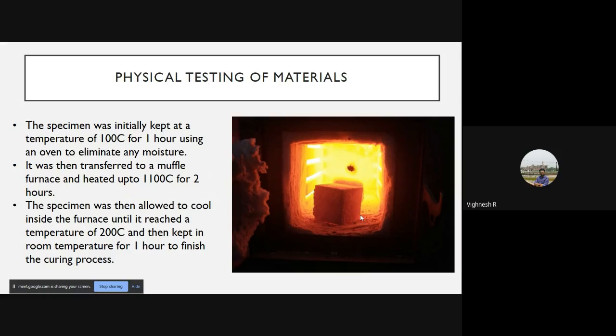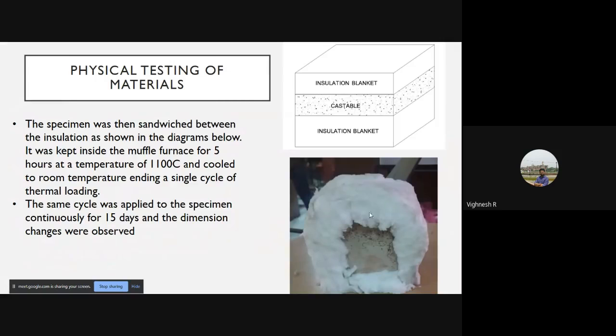That was a little different. After curing, we took the specimen and rolled it in insulation, as you see here. It tells you the practical situation which happens inside the furnace. The castable is sandwiched between two layers of insulation, as you saw in the first photograph. We kept it inside the muffle furnace and applied the temperature loading of 1100 degrees for 5 hours, and then took it out and kept it at room temperature for the remainder of the day. So it's a temperature loading cycle, similar to what happens in the field when the artisans melt the glass.